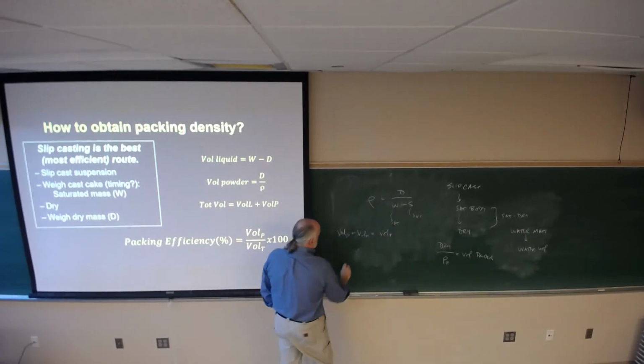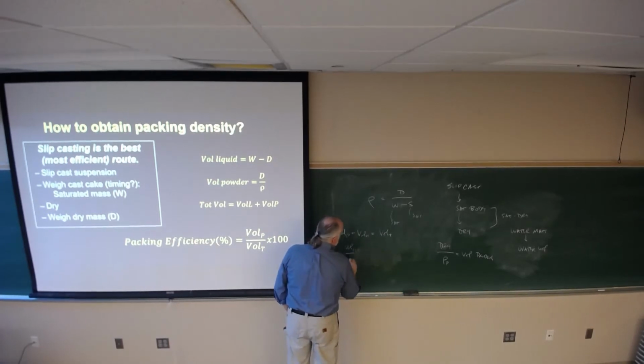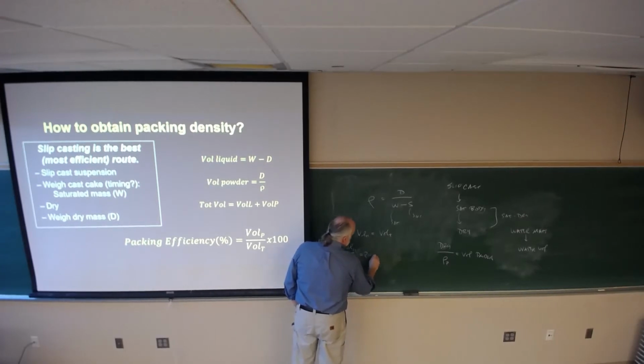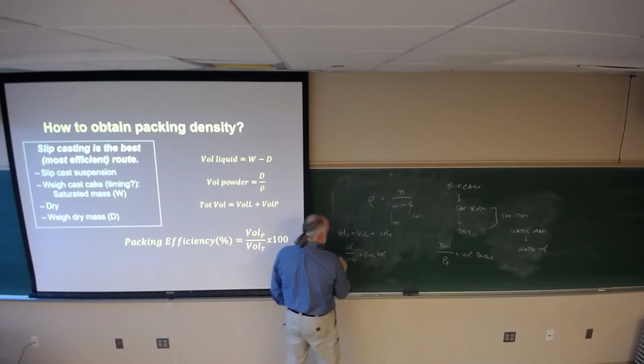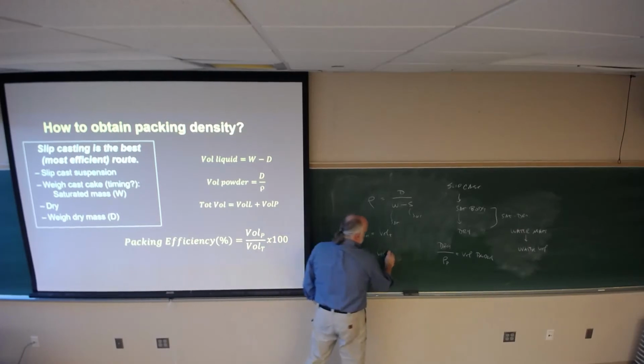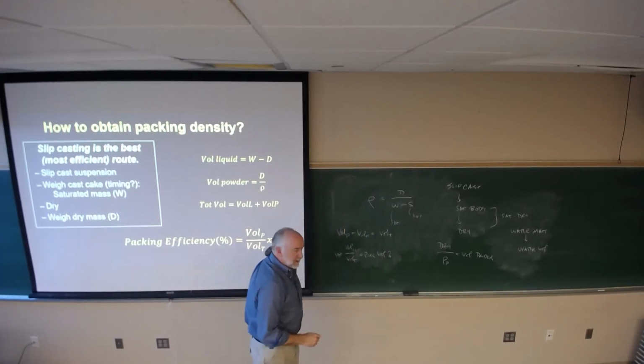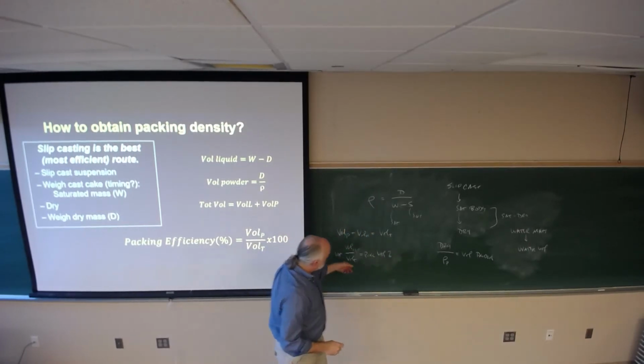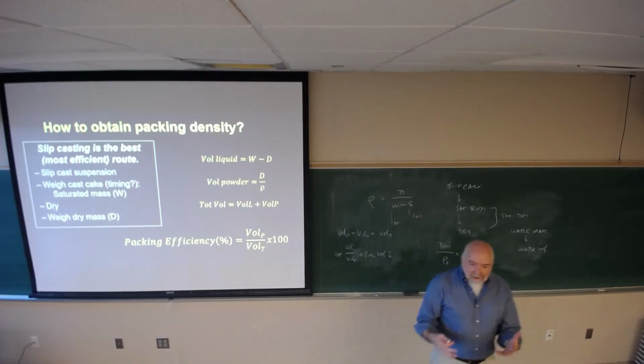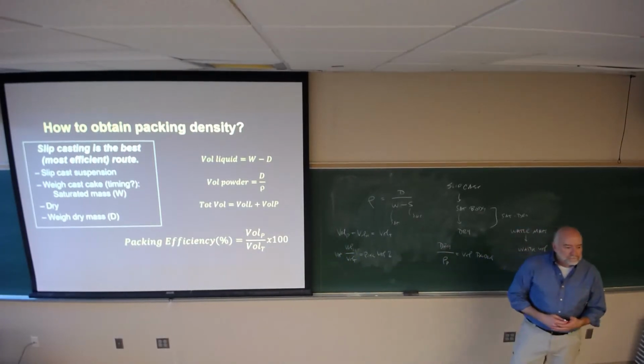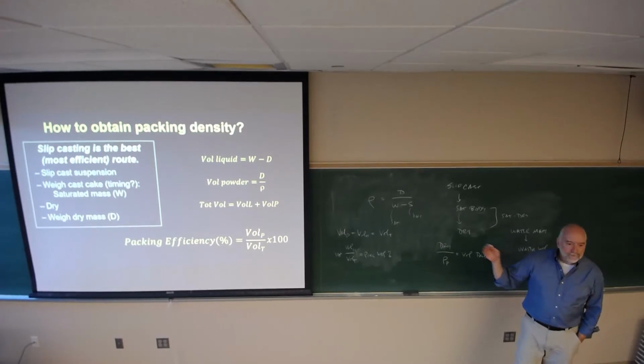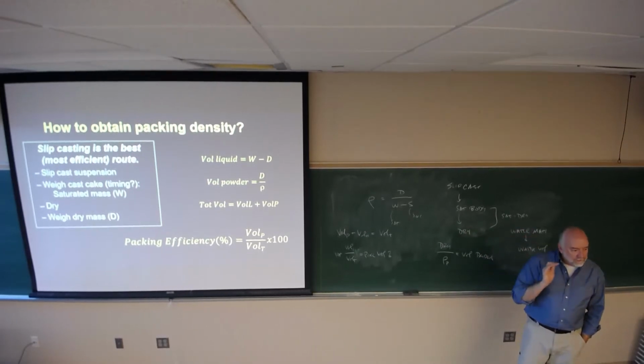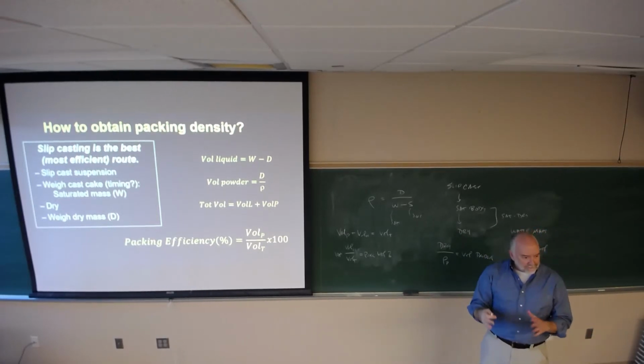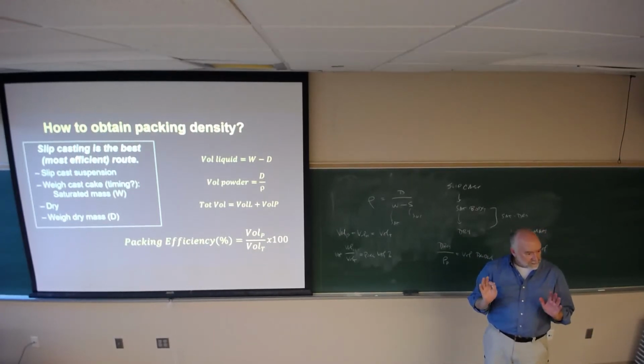And if I take the volume of water divided by the total volume, this is my pore volume. And if I take it times 100, I get a percent. Okay? And if I take the volume of powder divided by the total, I get the packing efficiency of the body. So this is fast. The only trick is that you have to figure out when that casting process is complete.